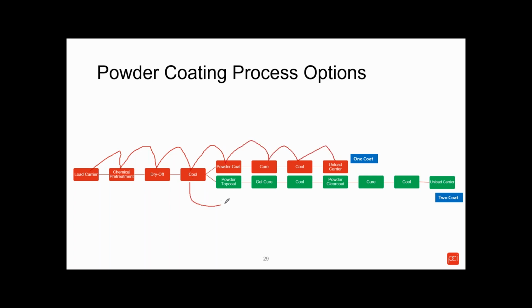On a two coat process, we would powder coat the base coat. We gel coat that, or gel cure, what's called B-stage cure. Basically flow that base coat, then cool it, then apply a clear top coat, and then go through a full cure, which would co-cure the base coat and the clear coat to fully cure the package, then cool it, and then unload it.